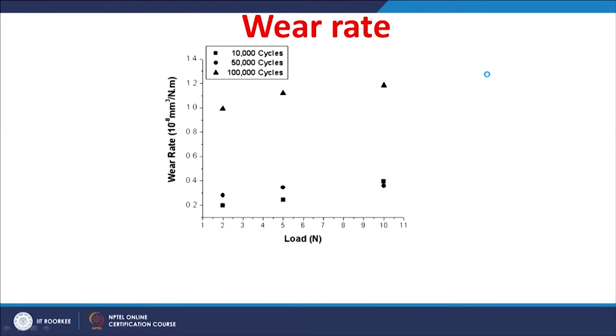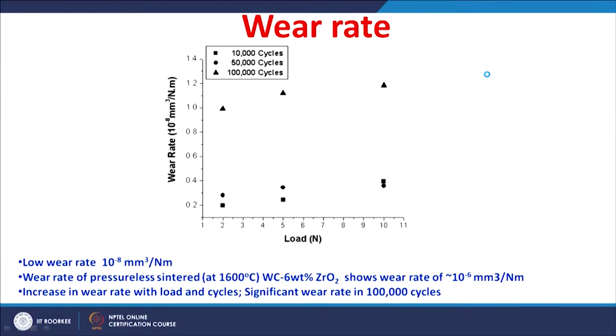The wear rate was also determined. So, you can see the wear rate varying from around 0.2 × 10 power minus 8 mm³ per Newton meter to around 1.2 × 10 power minus 8 mm³ per Newton meter. So, there is a change in the wear rate with change in the load as well as the number of fretting cycles. First of all, the wear rate is of the order of 10 power minus 8 mm³ per Newton meter.